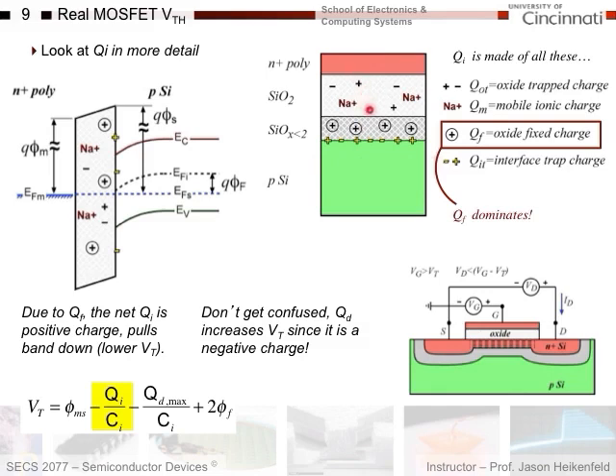Well, it has difficulty doing so right near the interface when it gets to here. And so right near the interface, you might not have all the oxygen you need to make perfect stoichiometric silicon dioxide, where you've got two oxygens for every silicon. If you're missing oxygens because you haven't got as many as you need down here to fully react this layer, then, since oxygen is electronegative, you end up with a net positive charge. This net positive charge shows up near the interface and will pull our bands down and reduce our threshold voltage. Again, we put this in the equation with a negative sign in front. This net positive charge ends up giving me a negative voltage here, pulling my threshold voltage down.